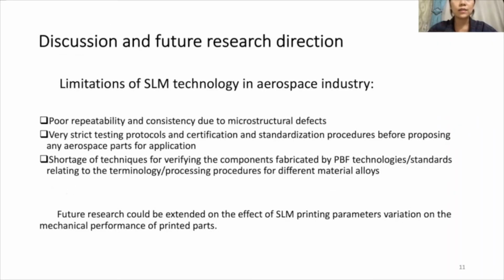So next slide is discussion and future research direction. The mechanical properties of SLM parts may be superior to those of the original counterparts, but reproducibility and test standardization are still an issue. Reproducibility problems can be due to microstructural defects caused by raw materials or processes and can be identified in several ways. Also, strength analysis is still an issue due to many phenomena like residual stresses, anisotropy, and porousness. Furthermore, there are very strict testing protocols and certification and standardization procedures before proposing any aerospace parts for application. The certification generally demonstrates the reproducibility of the manufacturing process and the consistency of the quality of printed parts.